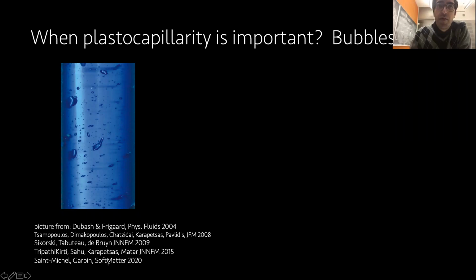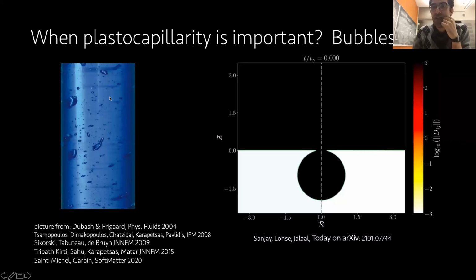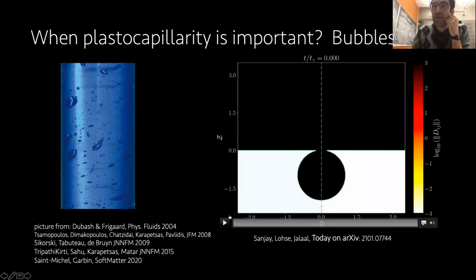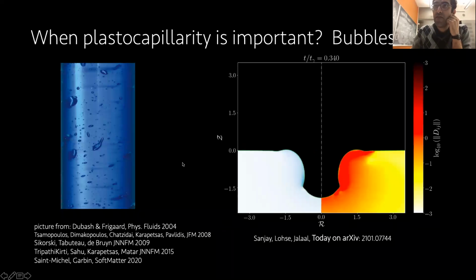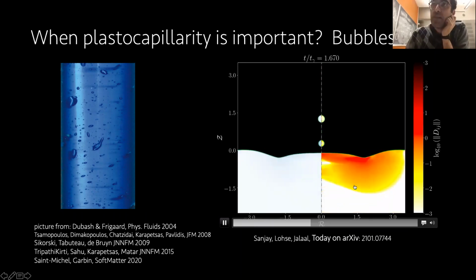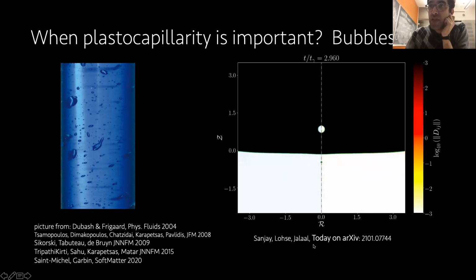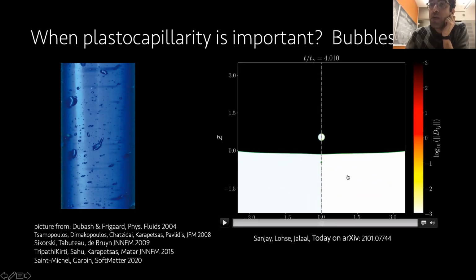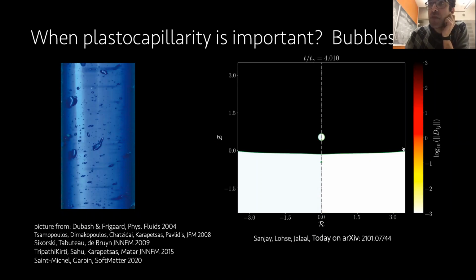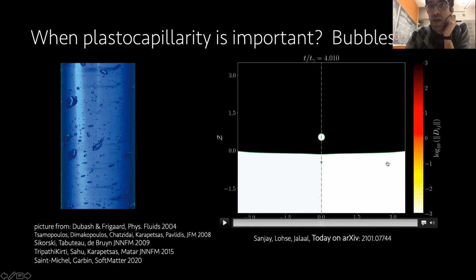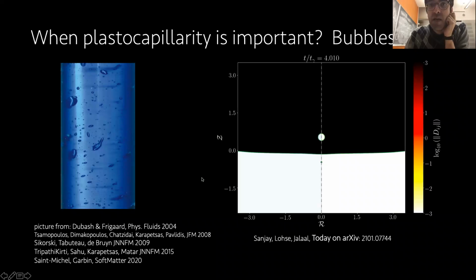More recently, the group of Valeria Garbin, now at TU Delft, also studied bubbles in yield stress material, in particular on acoustic actuation. Really nice, beautiful work. Our work on plastocapillarity and bubbles was slightly different from bubbles in the bulk of fluids. We looked into bubbles like this, reaching the free surface and then bursting at the surface. Again, I'm not going to go into the detail of this work either, but let me show a video. Basically, in this fluid, the bubble bursts at the surface, and the fluid is viscoplastic. In a work that actually came out today on arXiv, you can see how yield stress changes such a very dynamic process. In particular, you get this final cavity shape, which is characteristic of viscoplastic materials and doesn't happen in Newtonian liquids.